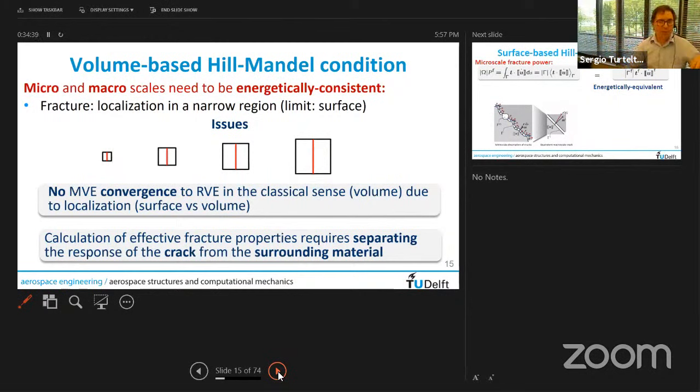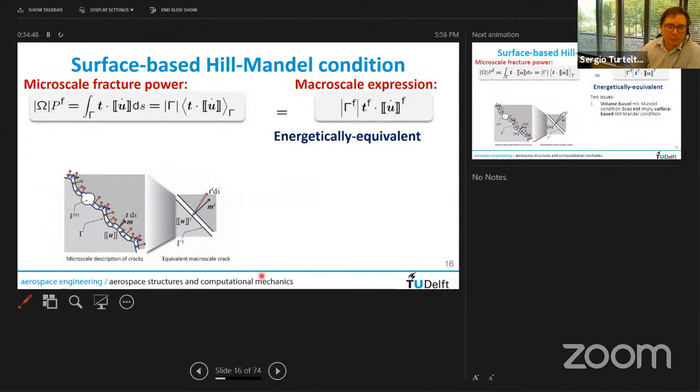How do we translate that into another type of Hill-Mandel condition? It's no longer a volume-based Hill-Mandel condition, but a surface-based Hill-Mandel condition. It's essentially very similar in the sense that you have to look at the power occurring through the fracture process. So we look along the crack, at the tractions and at the local crack opening rates, and you compute the power there. That integral is done along the crack itself. This is how you get the total power expended by opening the crack. And so the symbol here indicates this is a surface-based